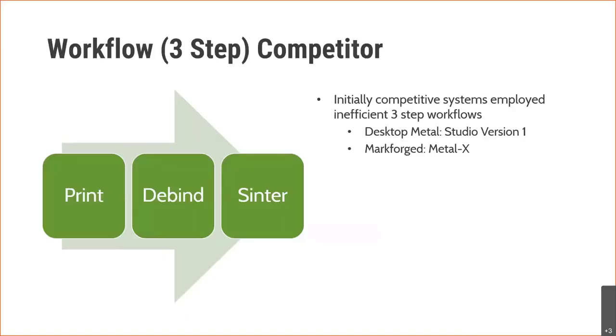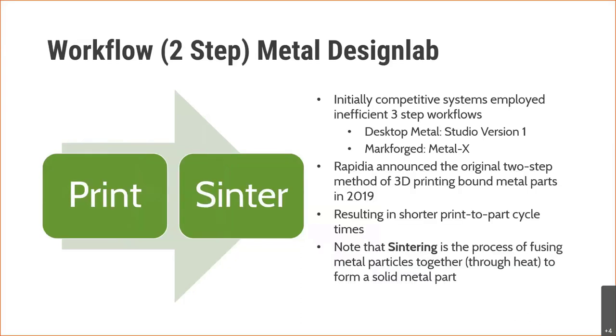The consumables themselves, I talked about them a little bit, and the workflow, but essentially, competitors have a three-step process, which means that you need to print, you need to debind and sinter, which, if you go back to the slide that I had illustrated earlier in the presentation, very much mimics that process. It mimics the MIM process, but we really don't need the debind process because we use water in the place of a lot of the binder that our competitors use. And so as a result of that, we have a very simple two-step process, as I mentioned before. You print it and you sinter it.